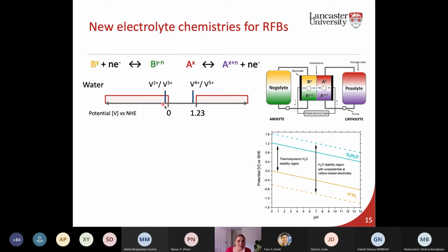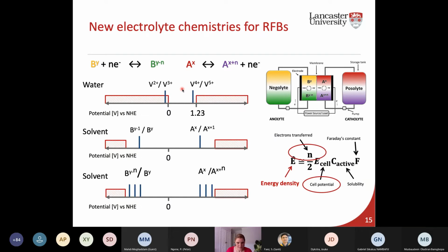But you're competing with those solution reactions as well. So whenever you're working out what solvent to work in for your electrolyte, you need to consider that you're competing with the reaction of the solvent and the salts as well. Aqueous flow batteries are quite confined to a two volt window, but really they're confined even less sometimes, because we want to avoid hydrogen evolution and oxygen evolution in the battery as well. So it really restricts where you can operate within an aqueous battery.